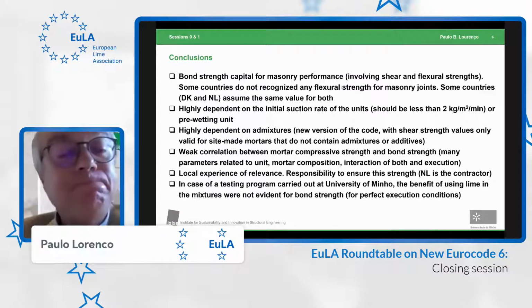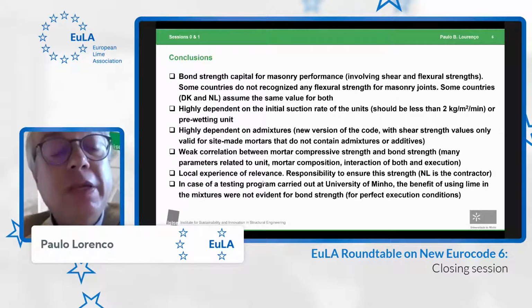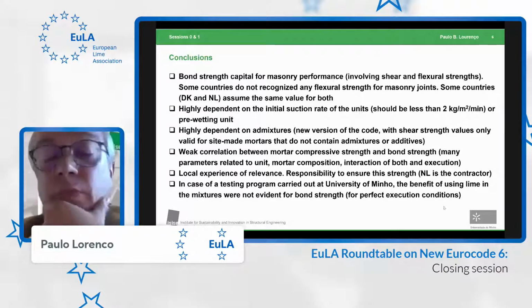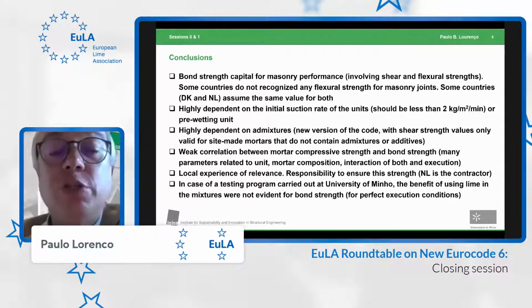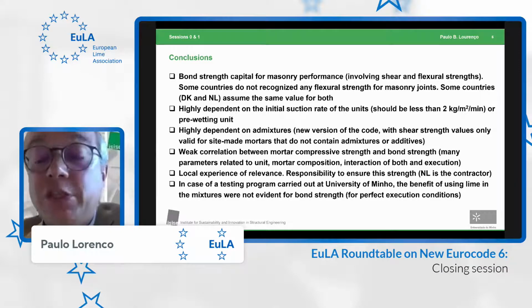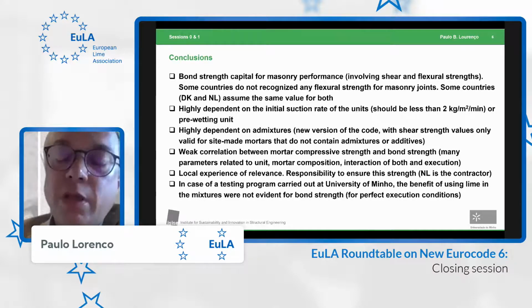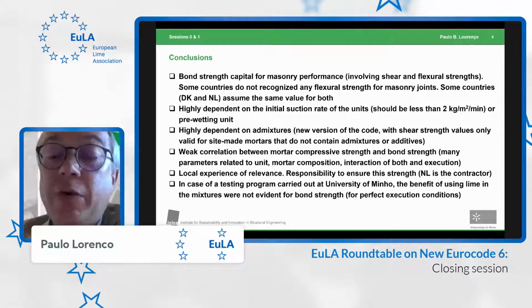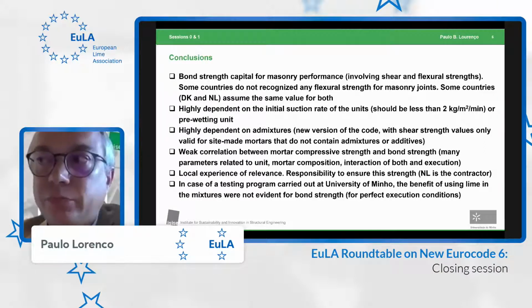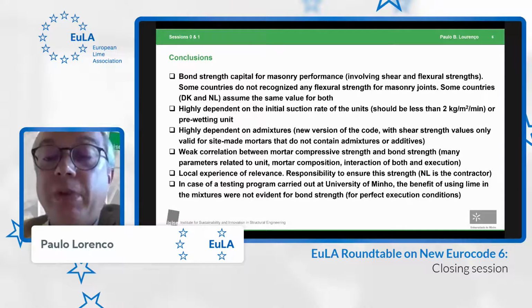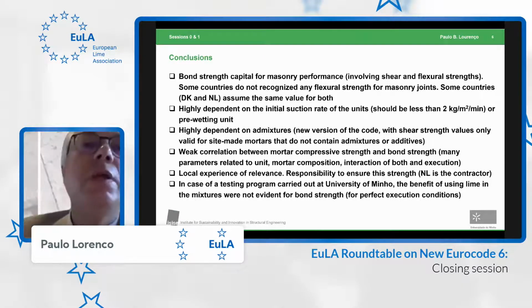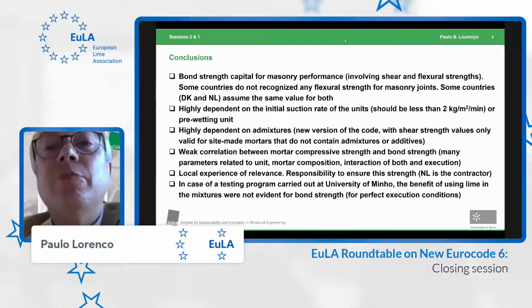And finally, in case of the testing program, the benefit of using lime was not very evident in the bond strength. And one of the issues is that perfect execution conditions were carried out in the testing program at the University of Minho. And this may not replicate directly the conditions in the job site. Okay, so thank you very much, and I move to Ulrika.